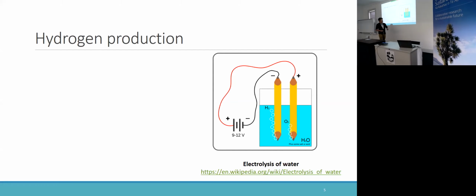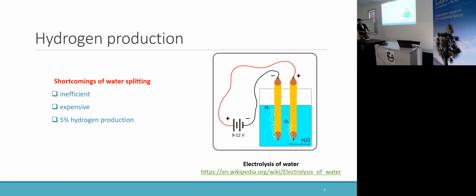In this case, we place two electrodes into a water bath, and then we turn the electricity on. The water molecules can be split into hydrogen gas and oxygen gas, and we collect the hydrogen gas from one electrode and the oxygen gas from the other electrode. This method is very clean, but it's also very inefficient and very expensive. As a result, only 5% of hydrogen is produced using this method globally.